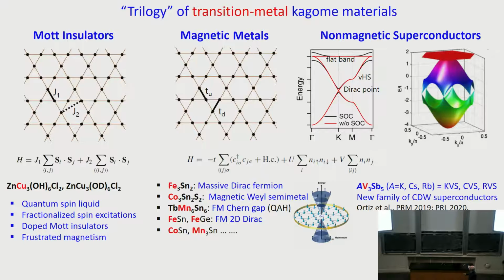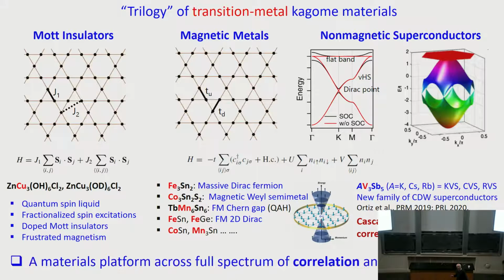Then about, how many? This is just the beginning of COVID, so 5 years ago, a new class of vanadium-based Kagome materials was discovered. And now these materials are non-magnetic, right? So they're non-magnetic. And then they become superconductors at very low temperatures. But it's more complicated than that because there's still plenty of correlation. They first turn into a CDW, a charge density wave ordered state. Then they become superconductors. In fact, there is a cascade of symmetry breaking and correlated states exhibited by these materials. So that, I think, is a fair introduction to the trilogy of the Kagome materials.